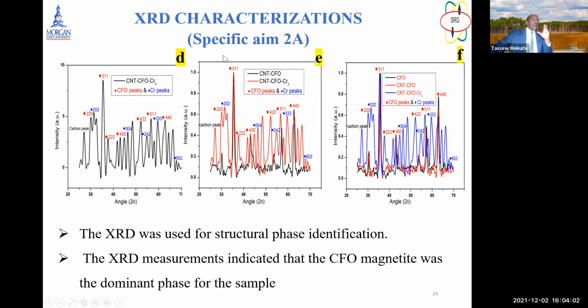So we continue to see all parameters together. We have CNT CFO peaks, CFO peaks, and the Cr peaks. And as you can see here, it is coming together by combining the graphs together. The XRD was used for structural phase identification, and the XRD measurements indicate that the CFO magnetite was the dominant phase for the sample, which is expected.